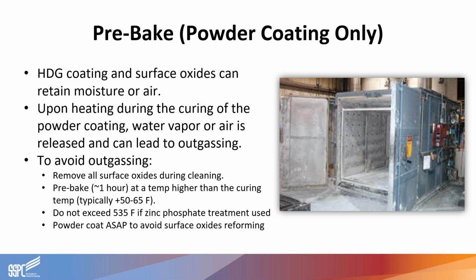The reason I bring this up is because ASTM D7803 includes a procedure for pre-baking that needs to be clearly communicated to all parties, what the pre-bake temperature will be. So it's typically about 50 to 65 degrees Fahrenheit above the curing temperature. For most powder coatings and equipment capabilities, this is not a big concern or issue, but at the high end of cure temperatures, you may need to consider capabilities and then consider any limitations if you're using that zinc phosphate treatment.